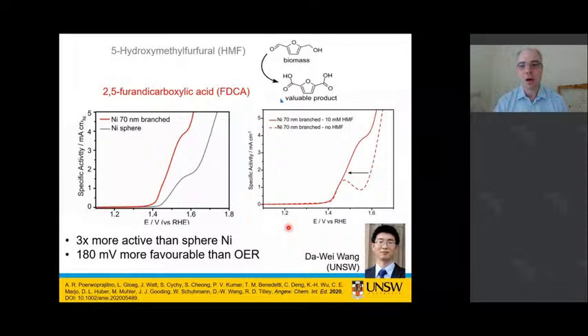So in terms of how we can go about designing or making better catalytic particles, one option is to take expensive metals like ruthenium and see if we can make them more active or more stable. If we're trying to make catalysts from more earth-abundant, cheaper metals, such as nickel, we can try and make them more active, but often that's quite a difficult challenge. One other option is that we look at using them as catalysts for reactions which are easier to catalyze or require less energy to catalyze. So we looked at the branched nickel particles for oxidation of biomass rather than as catalysts for the OER reaction.